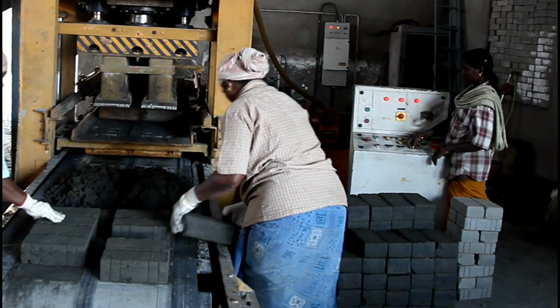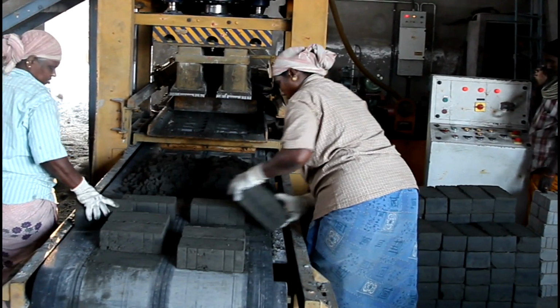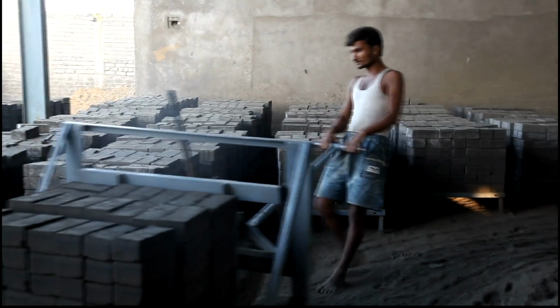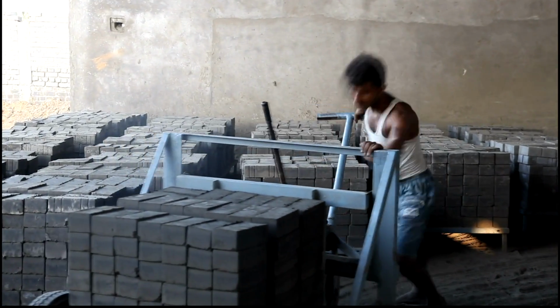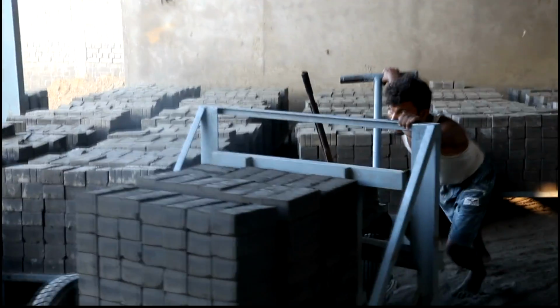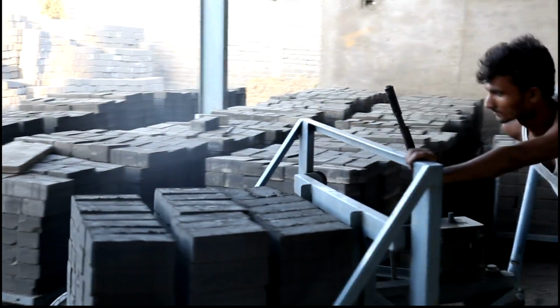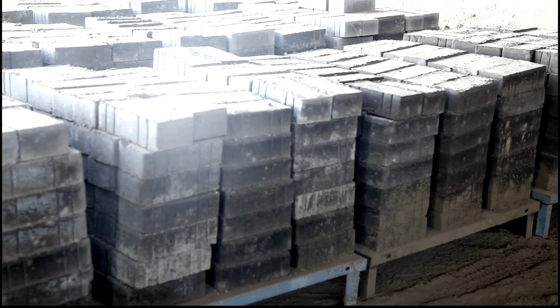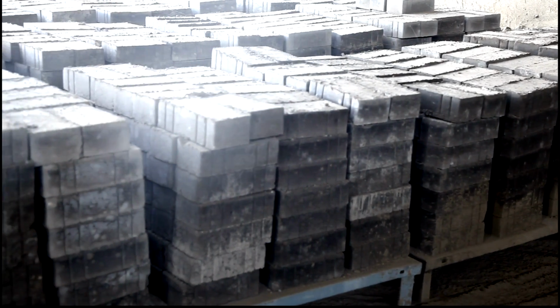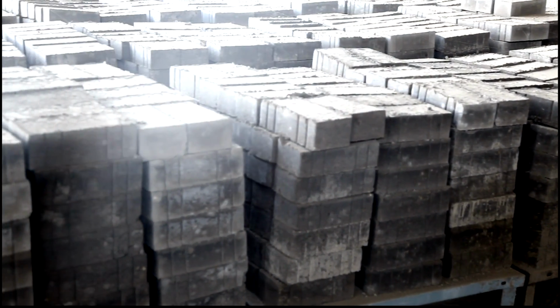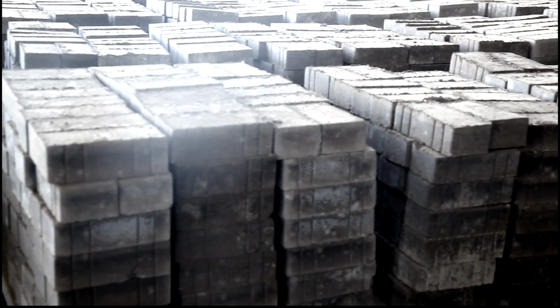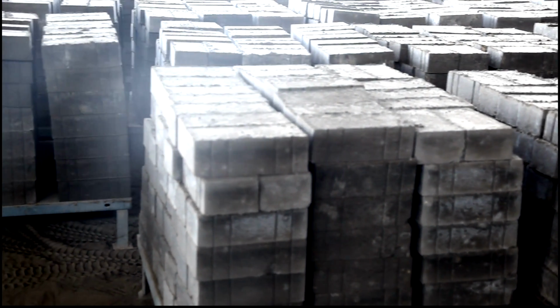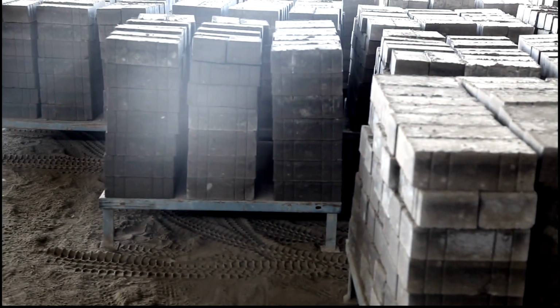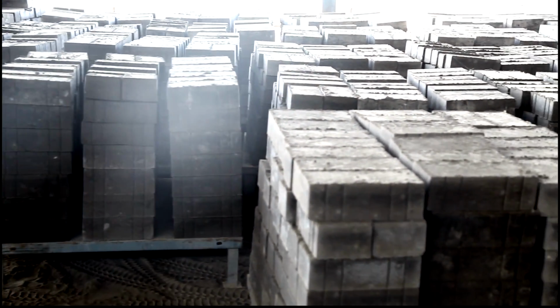The pressed bricks are taken manually and laid on wooden pallets in 4 to 5 layers. Pallets should be strong enough to carry the stack of green bricks without sagging. Brick-laden pallets are transported on a hydraulic trolley from the press area to the stackyard. Green bricks shall be air-dried for 1 to 2 days. Thereafter, air-dried bricks should be water-cured for a minimum period of 14 days. Curing is carried out by sprinkling water manually or by any other method. The curing period may be extended during cold and wet weather.